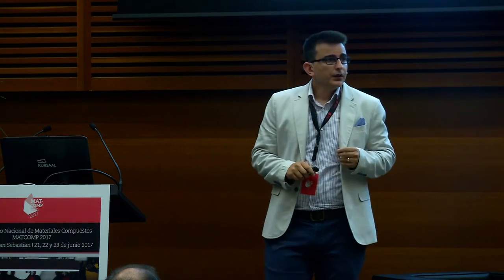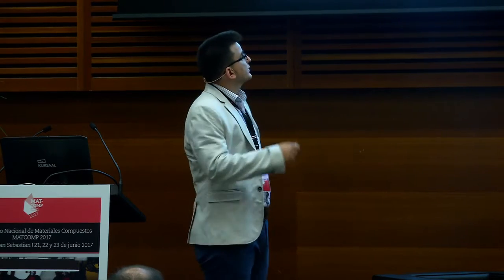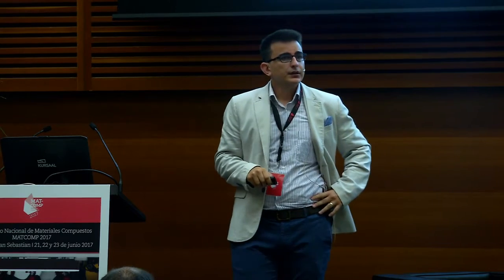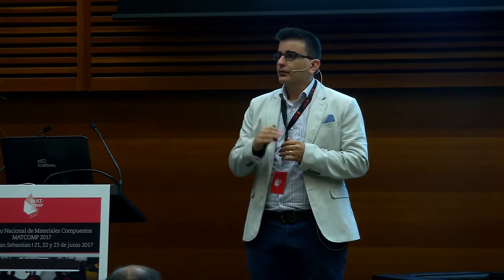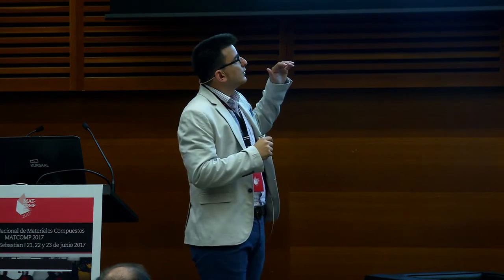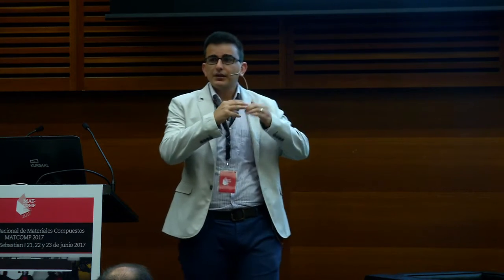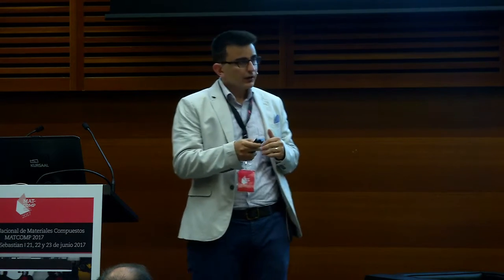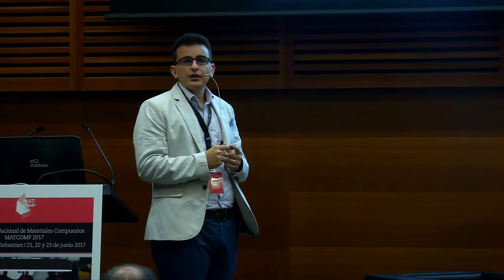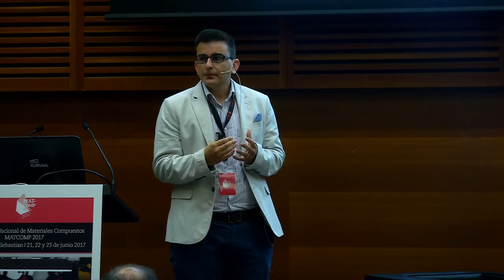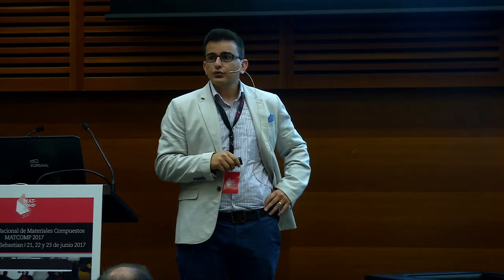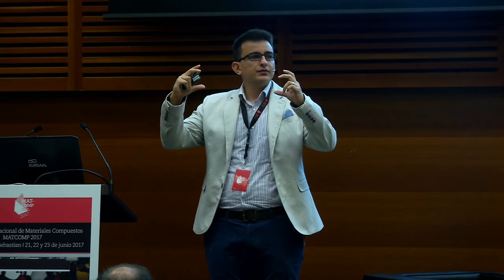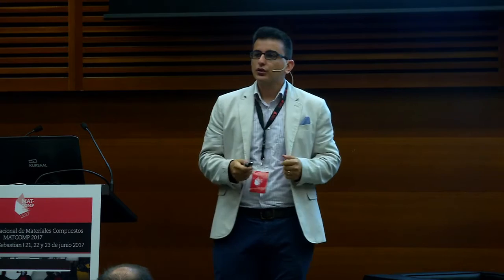Non-uniform curing is obviously very important, as we discussed with the delamination during the process. If we have a partially cured region inside the material, it's very likely to have a delamination of the laminated composite during the process. Again, this is due to a competition between thermal strains and the chemical shrinkage strain. So this is the delaminated pultruded profile just after the pultrusion die, because of the fast contraction of the outer surfaces and a partially non-cured center region. This profile is pulled with really high pulling speed, especially to see this kind of delamination.